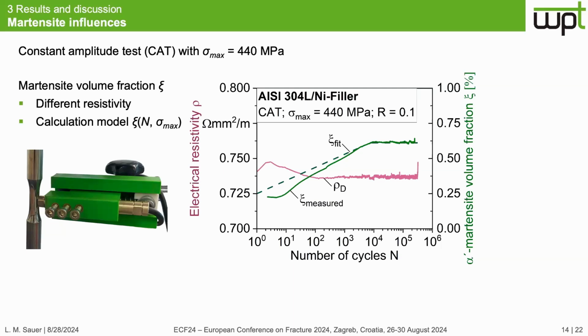But it was not possible to combine this ferrite scope with the previously shown measurement setup, so separate fatigue tests were performed, and a calculation model for the martensite volume fraction during the fatigue test was developed, which I'll not go into detail about because of the limited time. So as a result, the temperature-independent electrical resistivity of the austenite was determined, which, as mentioned, no longer depends on the geometry, temperature, or martensite. So from this, the microstructure changes can be evaluated.